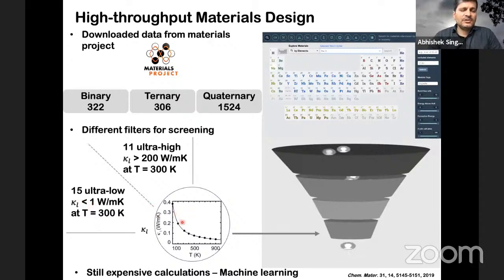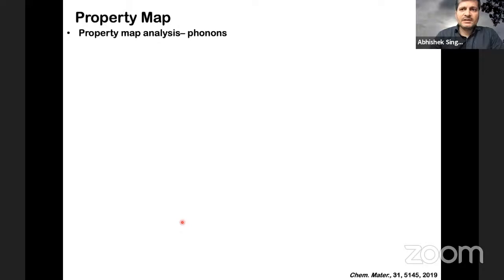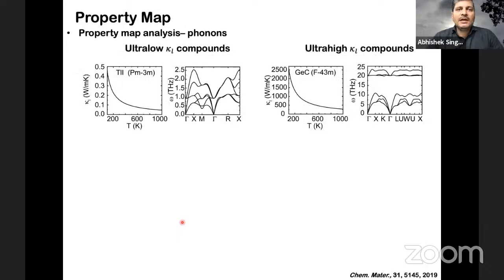Kappa L, or thermal conductivity, calculations are quite expensive. It takes about a week or so to get a thermal conductivity calculation for one compound. So what we did, this time for feature design, was to use just the property map, because now we had access to several properties, so we can create a property map. And what we found was that there was a correlation between some of the properties and kappa L.